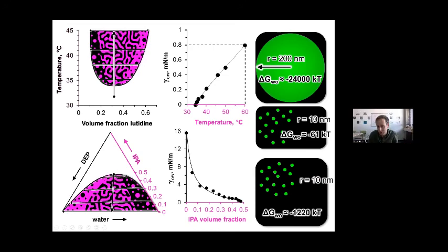Over time, it increases the interfacial tension because the two phases become more different in their compositions. The oil phase becomes more pure oil, the water phase becomes more pure water, because the solvent is removed. Initially, both the oil-rich and the water-rich phase still contain substantial amounts of the solvent, and that causes them to have a low interfacial tension. I wish it would immediately get a high interfacial tension, because then the nanoparticles would be very efficient in stabilizing the structure right away.